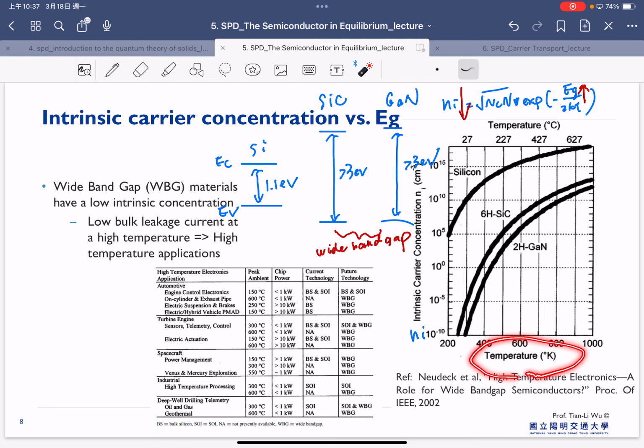But now with respect to different band gap materials, silicon has a band gap of 1.1 electron volt. Silicon carbide and gallium nitride have a band gap larger than 3 electron volt. So you can see that at a temperature around 800 K, silicon already has a concentration of more than 10 to the 15, but these two still have a concentration around 10 to the 10. That's actually about 5 orders of magnitude lower than silicon. So wide bandgap material has a lower intrinsic carrier concentration.